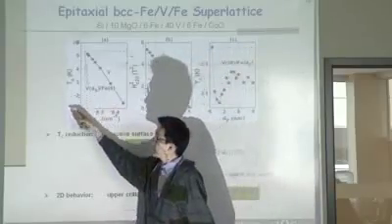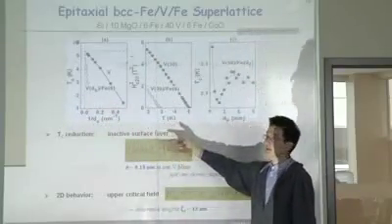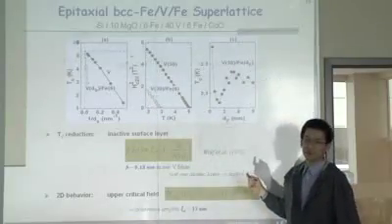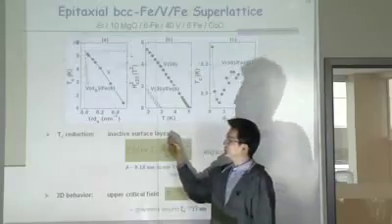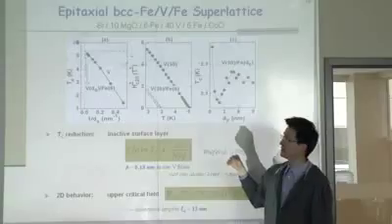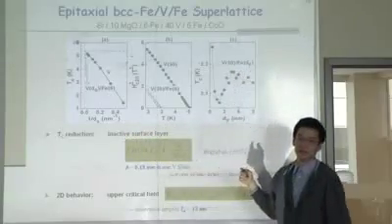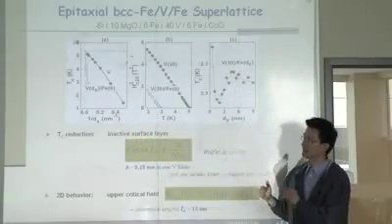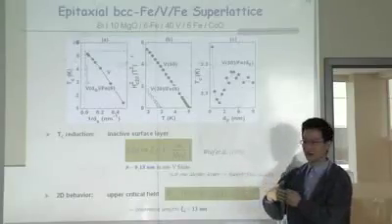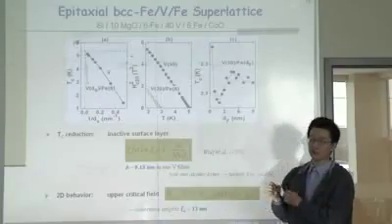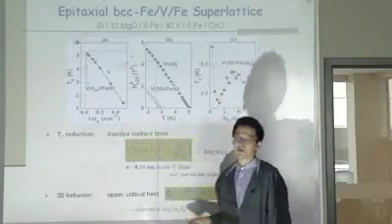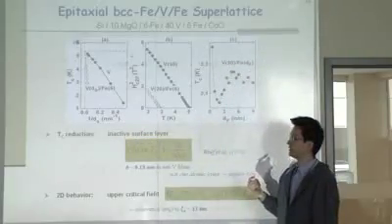We plot the transition temperature as a function of thickness. As you can see, the transition temperature is clearly inversely proportional to the thickness. This is quite well known in the literature because on the surface of every superconductor there is an inactive surface layer. The reason is that the electrons on the very surface do not have enough neighbors. On the other side is a vacuum, so they do not have a neighbor to pair up with to form Cooper pairs. So the surface layer will usually not have superconductivity.